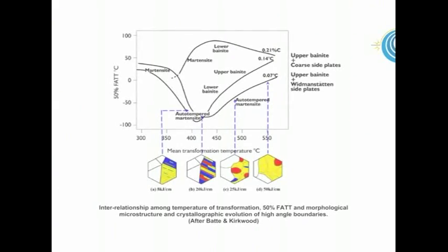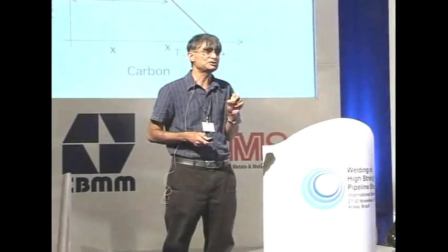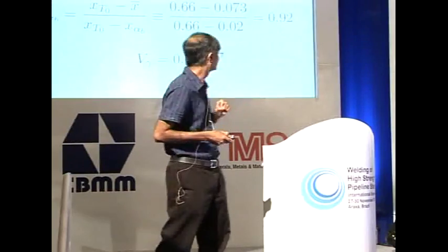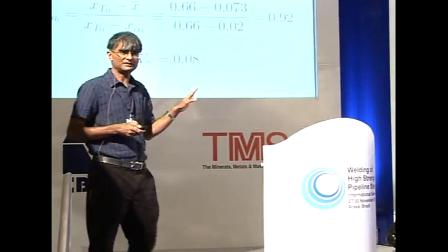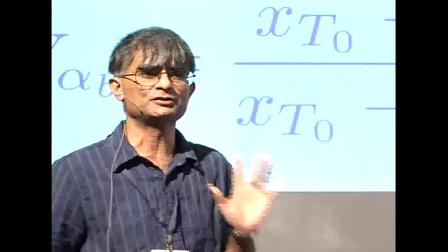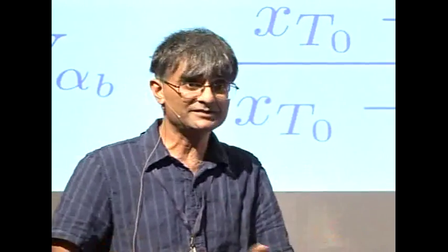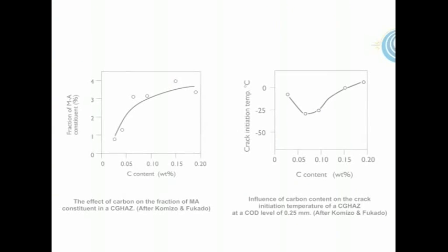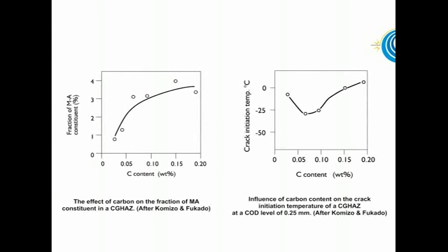Several authors at the seminar, including Professor Shang, presented microstructural analysis using the relatively novel electron backscatter diffraction (EBSD) technique. Professor Bhadeshia presented an interesting account of the way in which martensite-austenite (MA) constituent develops in heat-affected zone microstructures, and demonstrated how chemical composition and basic transformation theory could be used to predict its nature and volume fraction. As discussed in Dr. Kirkwood's keynote lecture, Professor Bhadeshia observed that MA was an inevitable consequence of the displacive bainitic transformation, and his explanation supported the view that carbon, and probably silicon, could increase the volume fraction of MA.